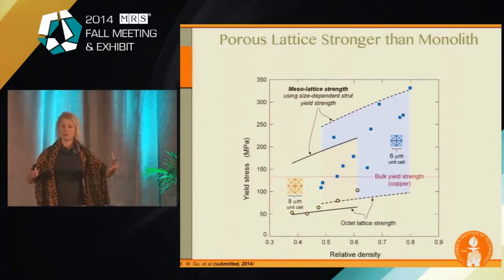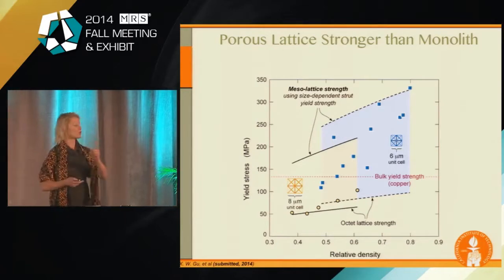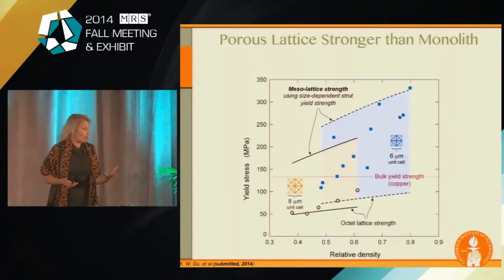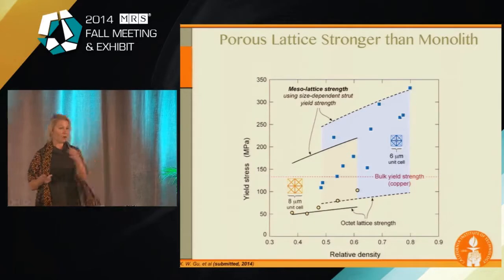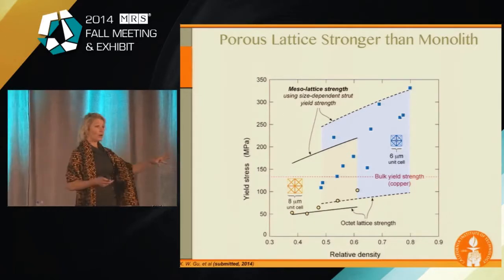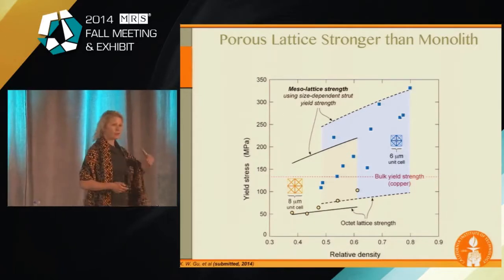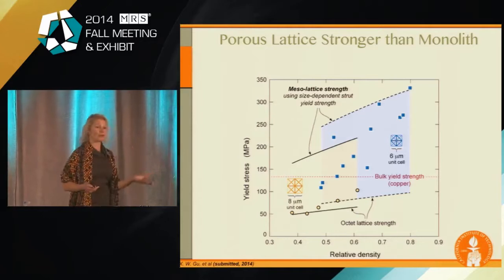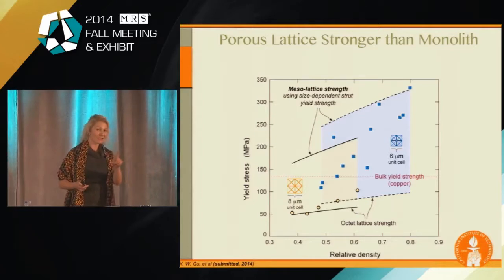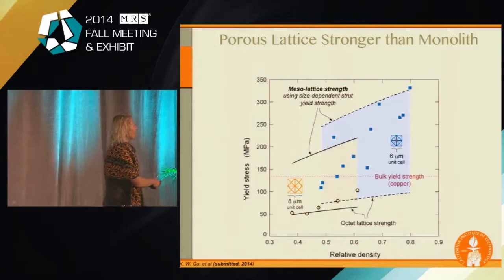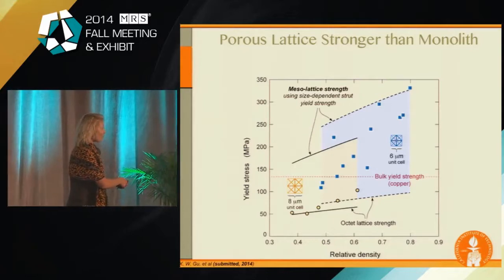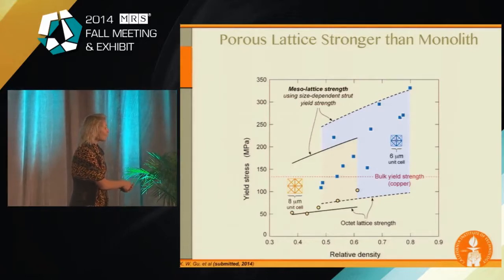Usually when you take something monolithic, and then you make a bunch of holes in it, right? We're going to pre-weaken it effectively. So the way you weaken a material is you put a whole bunch of flaws into it. You put a bunch of voids, you put a bunch of holes into it, and then when you try to compress it, of course, it should be a lot weaker. Not so much here. So watch this. This is the bulk yield strength of copper. This is monolithic copper. And now we take 20% of the material out of it, and its strength shoots up by a factor of 3.